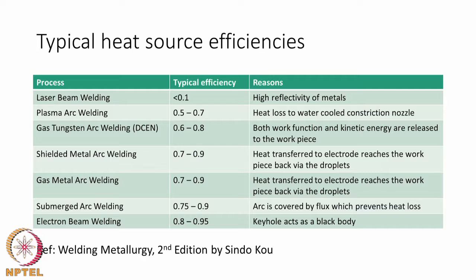Submerged arc welding also has a lot of efficiency, the reason being that the arc heat is not lost to the environment by radiation, because the arc is covered by granular flux which hides the arc and therefore prevents some amount of radiative loss. And electron beam welding is known to show efficiencies reaching nearly 95%, and the reason is as follows. The keyhole mode of welding that normally takes place during electron beam welding has a vapor column, and the vapor column acts like a black body to absorb all the energy given by the beam. Therefore, the entire heat is dumped into the material, and in that sense the efficiency of electron beam welding comes to be the highest of all the welding processes.